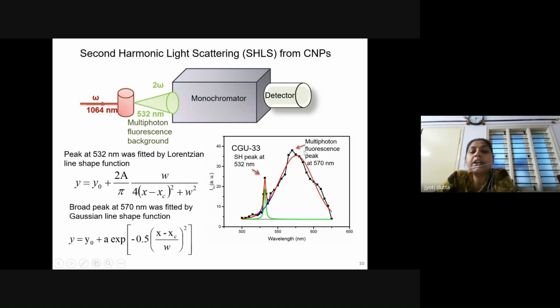Whereas the multiphoton fluorescence peak is a broad peak, which can include many broadening mechanisms, for example, solvent broadening and the involvement of multiple excited and emissive states. So this is how we have separated the contribution of multiphoton fluorescence from the second harmonic peak and the contribution of the second harmonic signal from the multiphoton fluorescence peak.